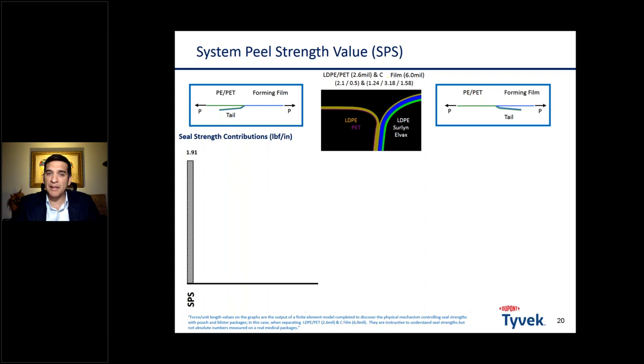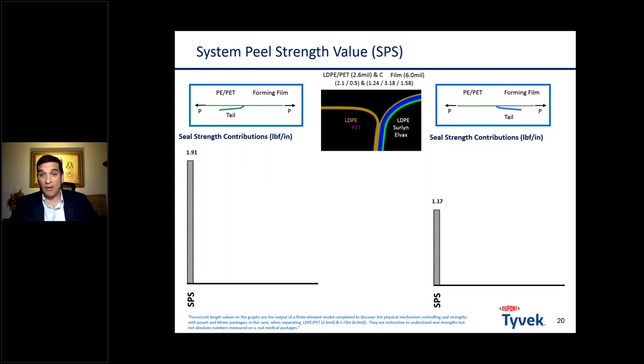If I bend back towards the polyester, my system peel strength in this particular example was 1.9. Now, in the second sample, the peel strength is 1.17. So why is that the case? We were able to do a finite element analysis of the materials to quantify where those energy absorption points were coming from. And this is what we found.